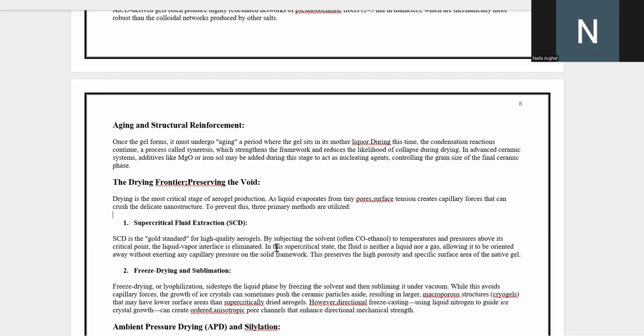Creating an aerogel's delicate air-filled structure is the hardest part of the process. The final and critical step is drying: removing the liquid from the wet gel without letting surface tension crush the teeny nanoscale pores. Imagine the solid network as a fragile sponge made of drinking straws. If you simply let the liquid evaporate, the surface tension at the liquid-air boundary would create powerful inward forces, collapsing all the straws. To avoid this, scientists use special drying methods that bypass this problem.